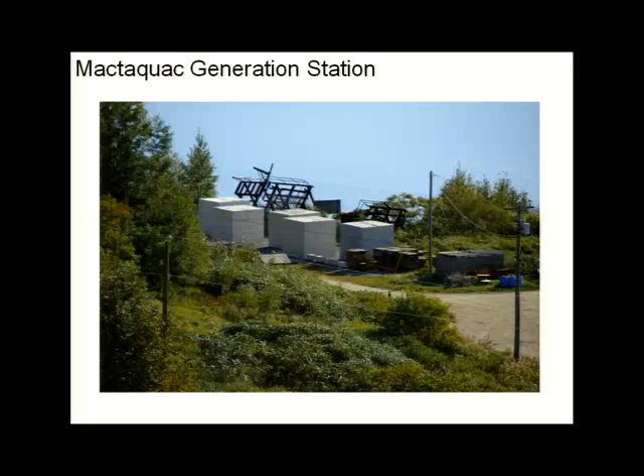But there are a lot of drawbacks to the test. One, it's overly aggressive, so it tends to fail a lot of aggregates that may pass in the field, meaning they're not going to have ASR problems. You also end up with the risk in that test of having a false negative, where it tells you that the aggregate isn't going to be reactive, but it actually is in the field.